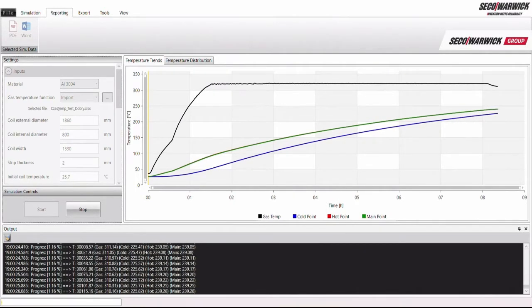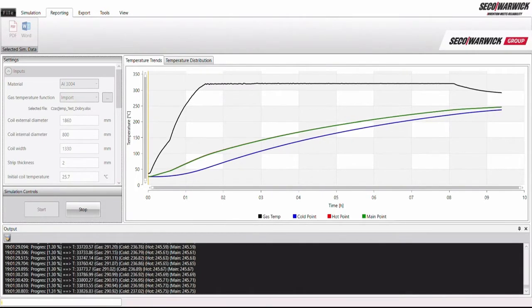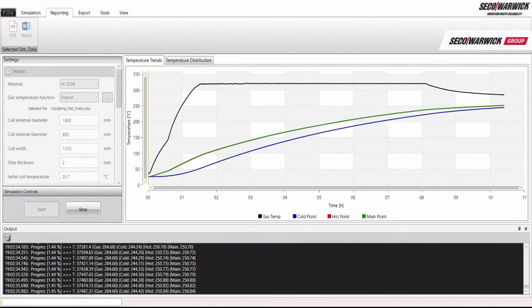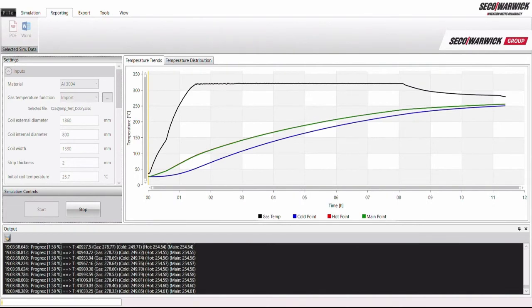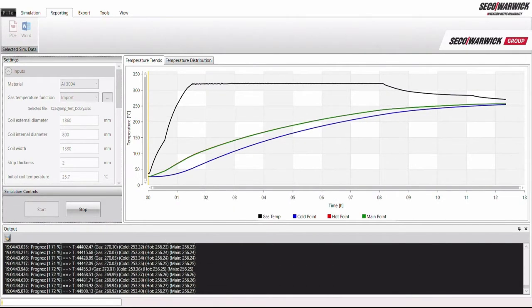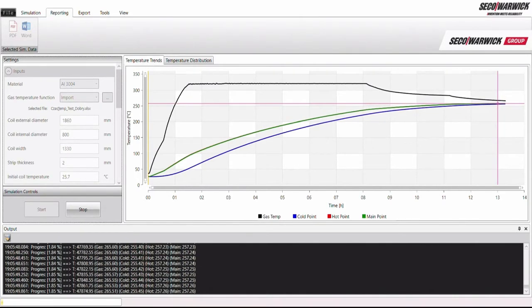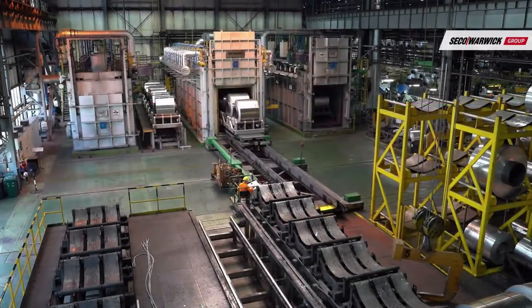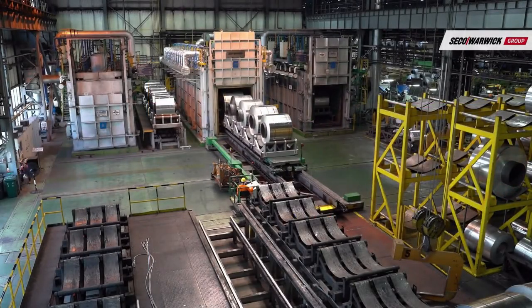The task of the automatic regulation and control system is to maintain a certain temperature excess in the heating chamber until the appropriate, safe temperature is reached at the virtual measurement point, and then to lower the temperature of the heating chamber according to a strictly defined relationship. Thanks to the applied procedure, it is possible to obtain the shortest possible process time without the risk of overheating the coil. The following advantages of the SICOIL system can be mentioned.